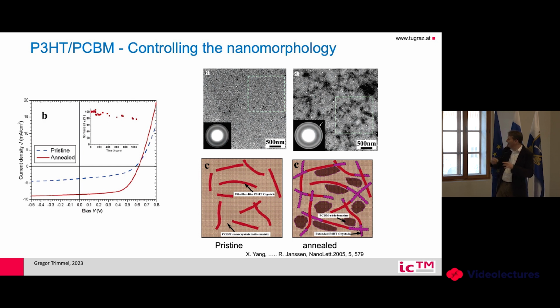So you need the morphology. The interface for sure is lower than in the first one, but you have larger objects also. And then you see that the red curve, I think you clearly see it, is much more efficient. The efficiency was more than doubled compared to the original case. The reason is that, of course, you need this interface.